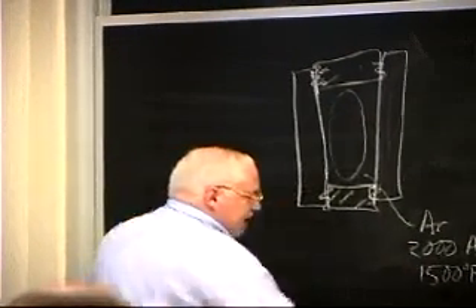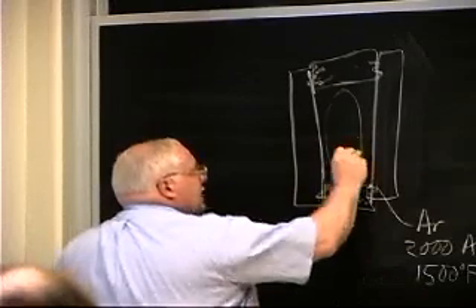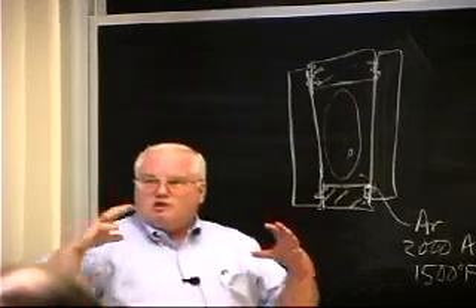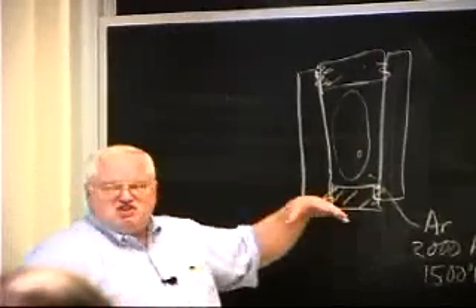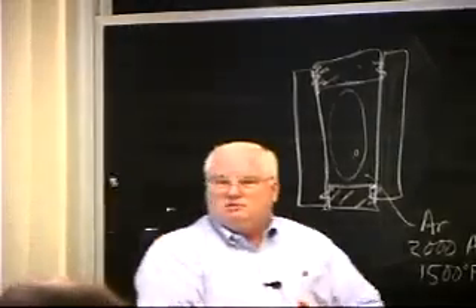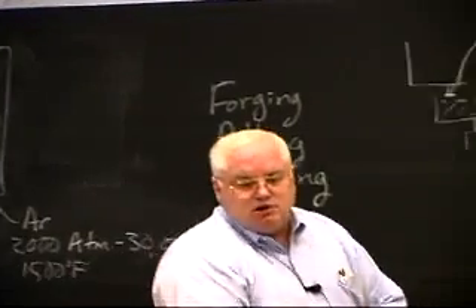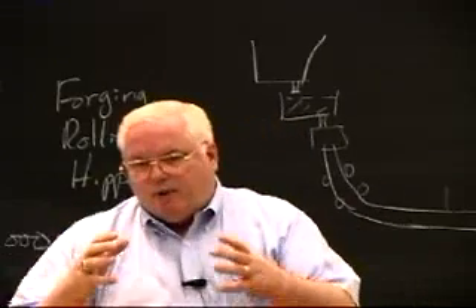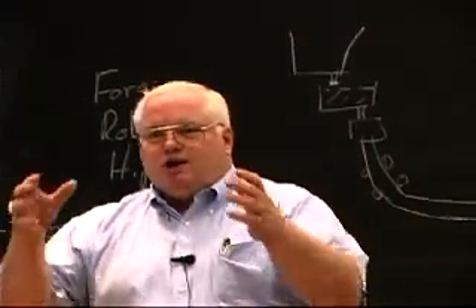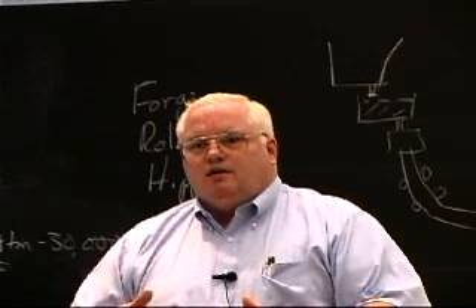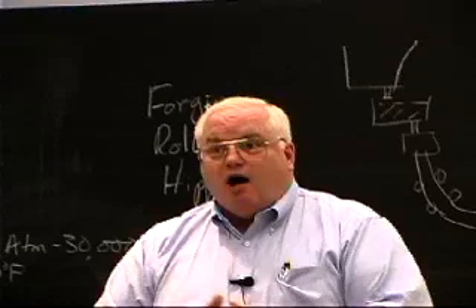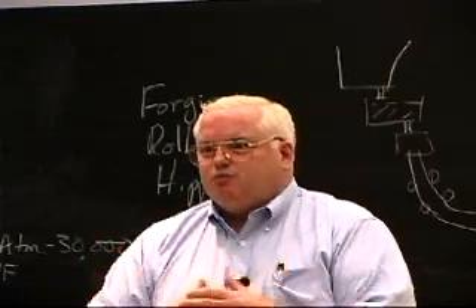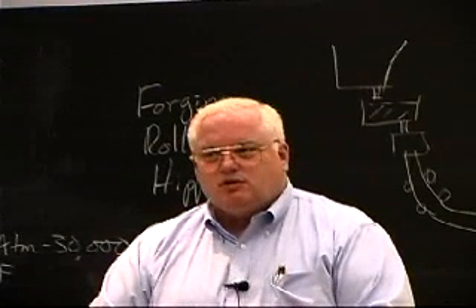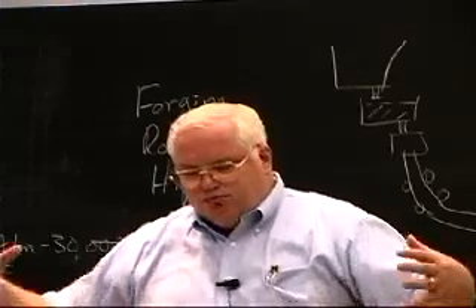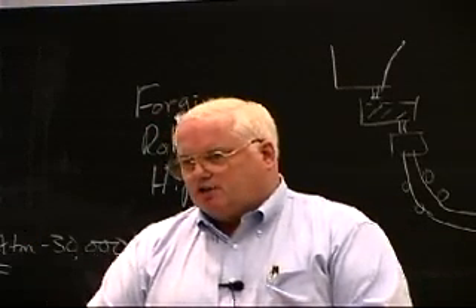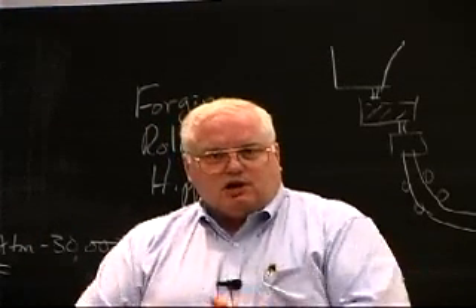And so basically, if I have a casting in here with pores and I heat it up to these temperatures where the metal becomes softer, I basically just squeeze the porosity out of it. And so I can basically take a powder metallurgy part and put it inside a can and weld up the can to keep the argon out, because I can't have gas in between the pores or I'll just trap gas in the pores. And I put it in a hot isostatic press for a 10-hour cycle and take it out, and I've got a solid part.